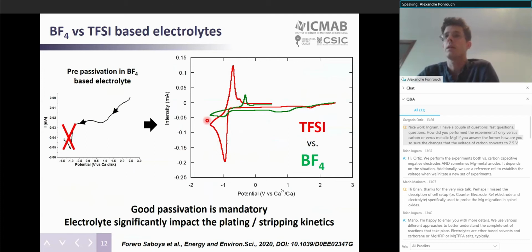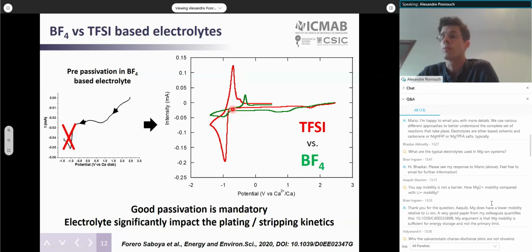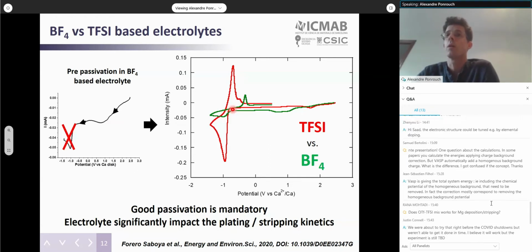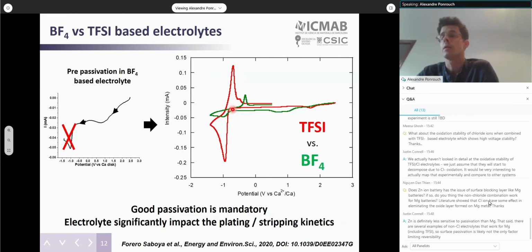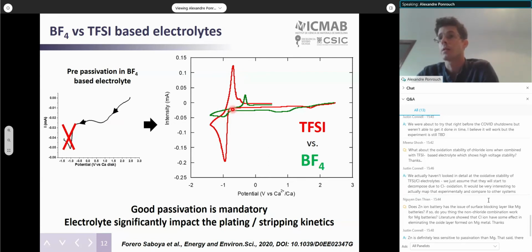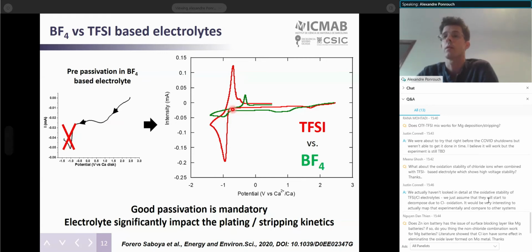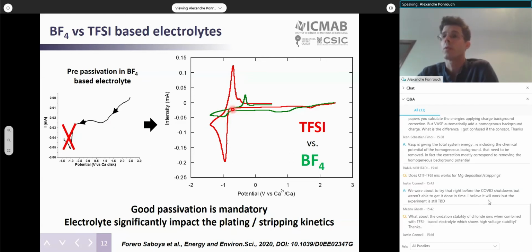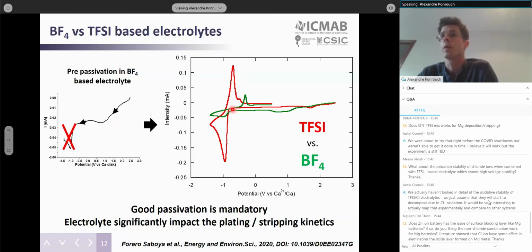As you can see, not only do we observe calcium plating and stripping in the case of the TFSI-based electrolyte, but in the presence of this pre-passivation layer, we also observed a significant increase in the calcium plating and stripping rate—almost a fourfold increase in the plating stripping kinetics when compared to the BF4 based electrolyte. So there is definitely a role played by the passivation layer.